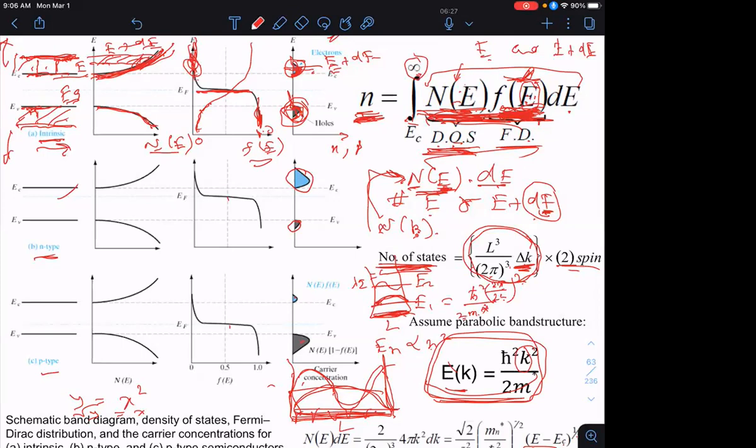That information is given by the density of states, which itself is a function of energy, N of E. And the meaning of N of E is that N of E times an energy increment delta E is the number of allowed states between an energy E and E plus delta E, okay? And that's shown graphically in this second column. We won't prove it, I'll sort of make it plausible, that this is a parabolic shape, and that's why these are known as parabolic density of states.